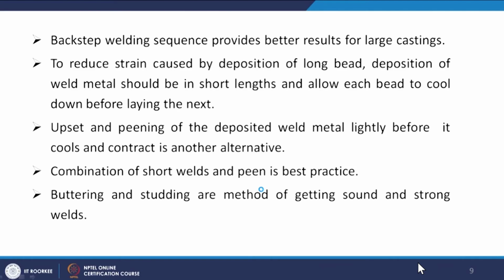Backstep welding sequence provides better results for larger castings to reduce strain caused by deposition of a long bead. Deposition of weld metal should be in short lengths, allowing each bead to cool down before laying the next. Upsetting and peening the deposited weld metal lightly before it cools and contracts is another alternative. A combination of skip welding and peening is the best practice. Buttering and studding are methods of getting sound, strong welds.